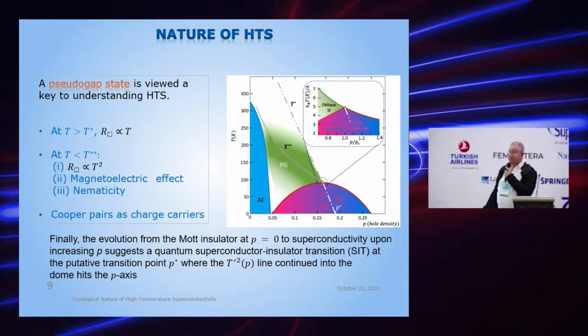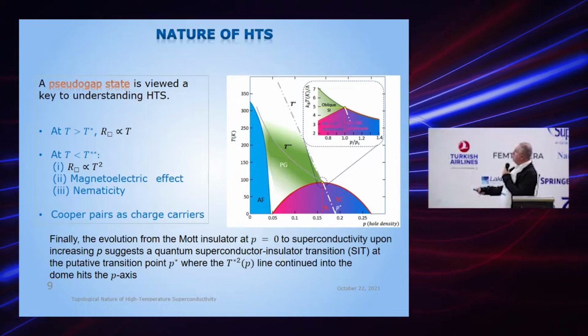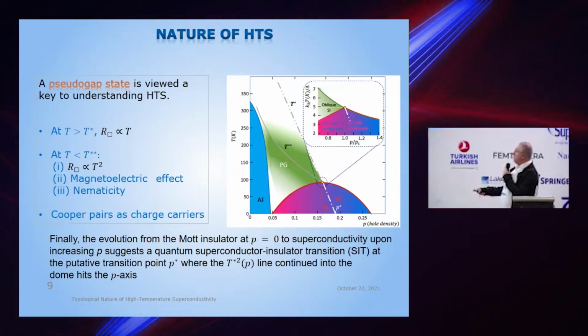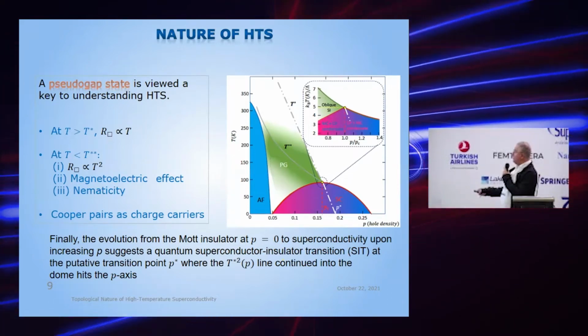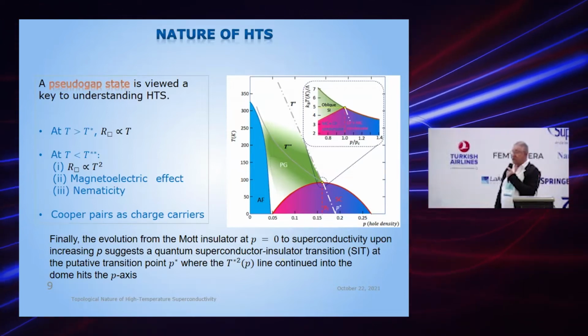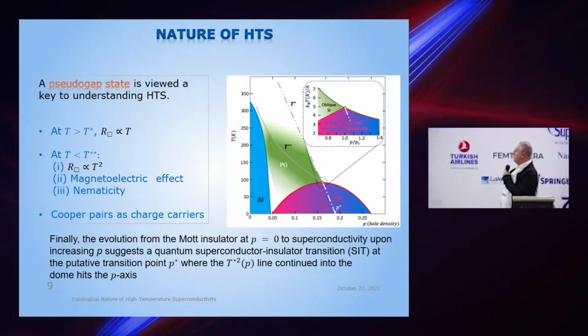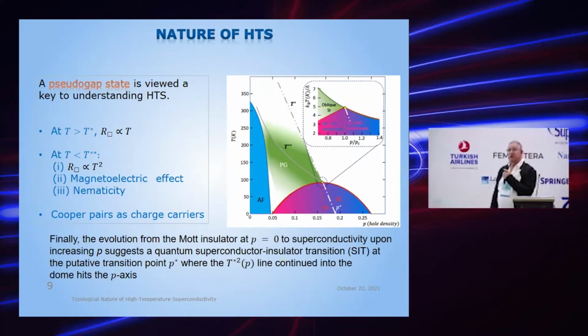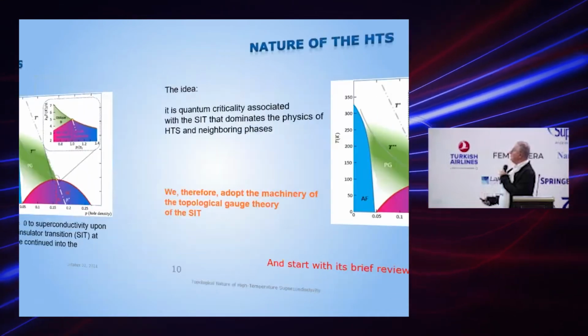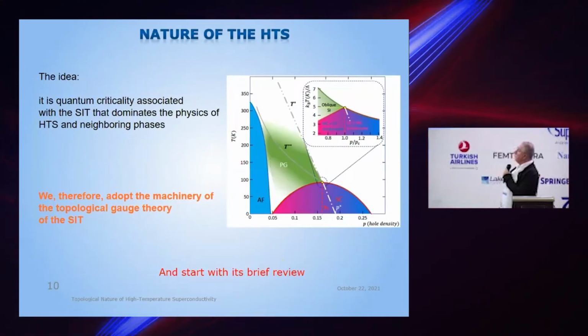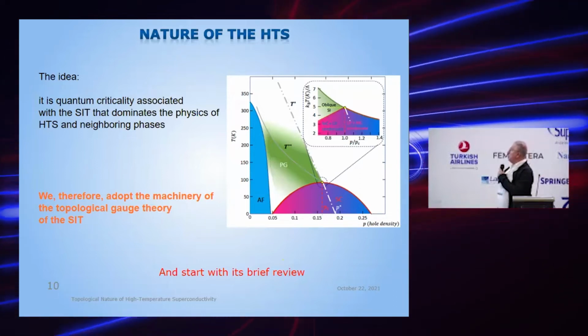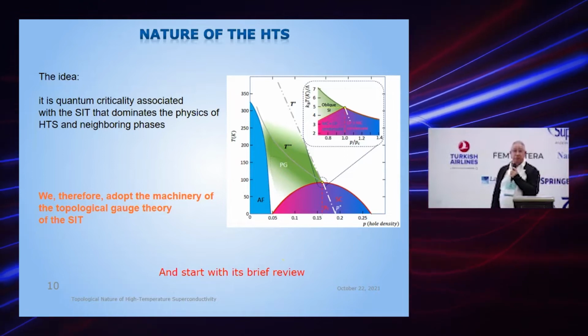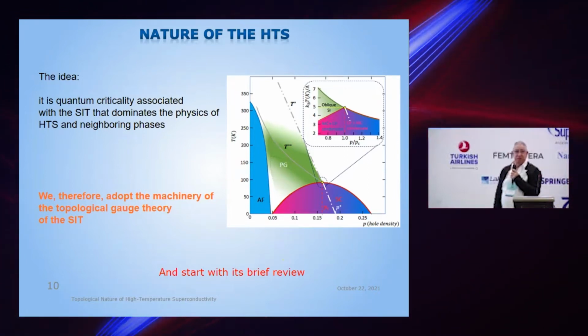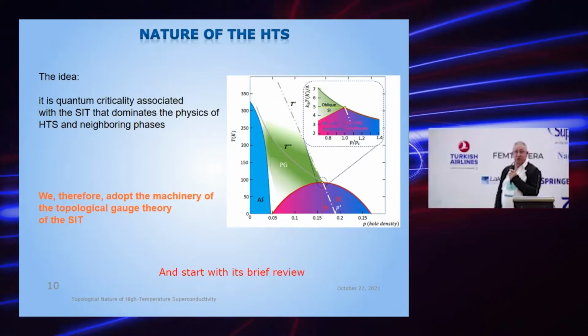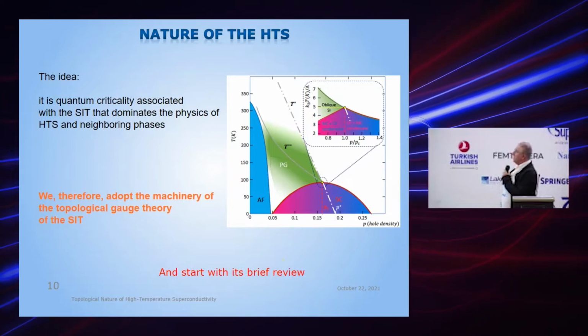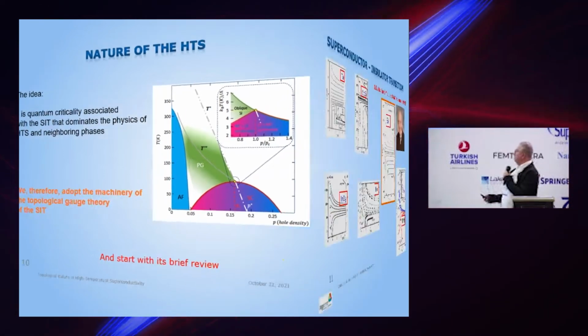So what is well established is that we have an antiferromagnetic Mott insulator at low doping, and then somewhere we have this quantum phase transition, probably from the Mott insulator to superconductivity, and everybody agreed that it is this quantum phase transition which dominates the physics of high temperature superconductors. And therefore, in order to resolve all the problems of high temperature superconductivity and explain its mechanism, we will apply all the machinery for the description of the superconductor to insulator transition, and start with a brief overview.